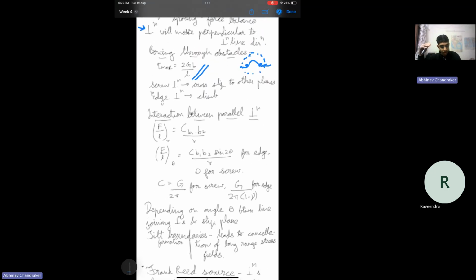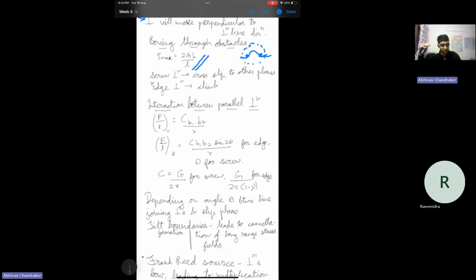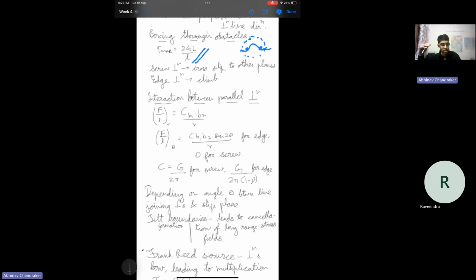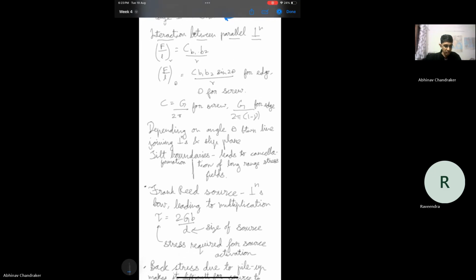Sir has not explained this in a lot of detail. In short, he had explained. The reason for this is that a screw dislocation has only a line associated with it, because the Burgers vector is also along the same dislocation line. But an edge dislocation is defined by a plane, because the Burgers vector is perpendicular to the dislocation line. That defines a plane, so it cannot change that plane. If it goes to a different plane, then the Burgers vector will no longer be in that plane. That's why an edge dislocation can only climb. And climb is a phenomenon which involves the diffusion of vacancies, which leads to a movement of the extra half plane of the edge dislocation.